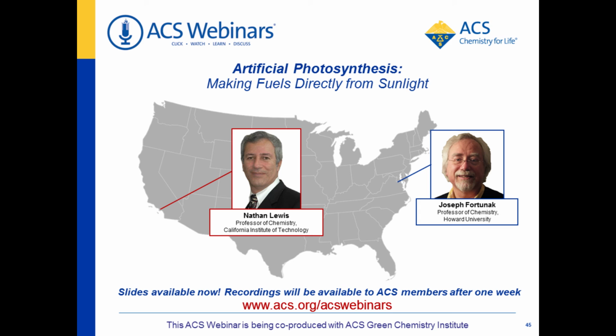We don't see any role for near neutral pH stable water oxidation catalysts because we can't build an efficient, safe system there. It would be helpful to get replacements that are lower in overpotential for water oxidation in alkaline media, but it's only incremental because the catalysts we have, the iron nickel oxyhydroxides, are already pretty good. If we shaved another 100 millivolts of overpotential off, we would do a little bit better. And so that would be a good step, but it's not the big lever. The big lever is the light absorbers from where we are now.